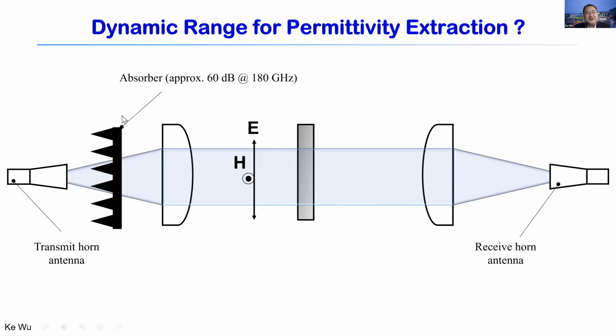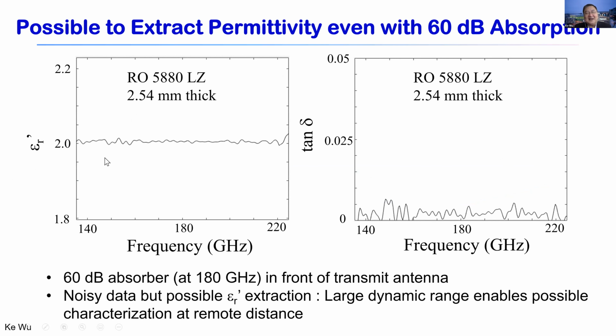At the same time, if your input power is not high enough, we talk about dynamic range. How good a dynamic range can we get for the measurements? In this case, we use an absorber. The absorber gave roughly 60 dB attenuation at 180 gigahertz. So in this case, very weak power comes out of this system and goes through the sample under test. Even in that case, we can still get pretty good, decent results. So it is very satisfactory.